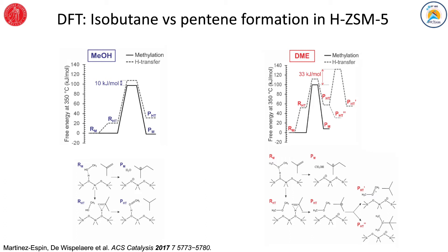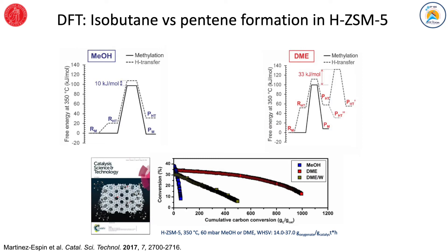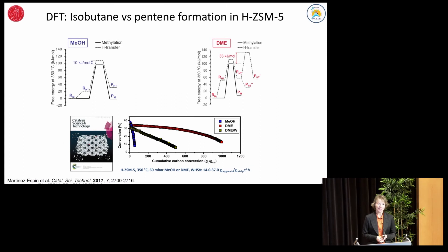Based on these studies, we later performed a comparative study between methanol and dimethyl ether as feedstock for the methanol to hydrocarbons reaction. As expected from the mechanistic studies, a far higher oxygenate conversion capacity was observed when starting from dimethyl ether than from methanol. This study constitutes an example of insight-driven process design.